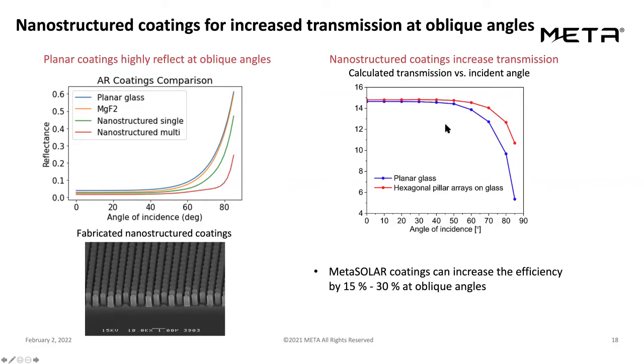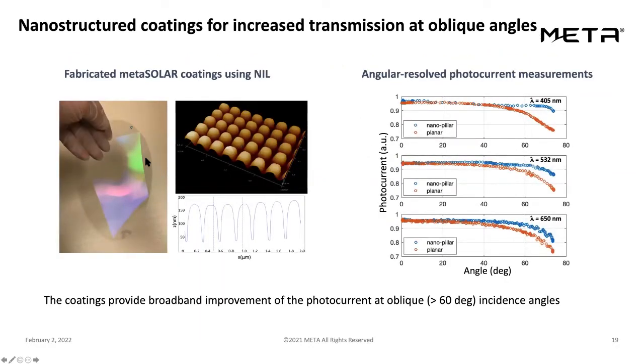And on the right-hand side, you see the total short circuit current for a 3-5 cell with an optimized coating in red, and then the planar glass is in blue. You can see an increase of 15% to 30% depending on the angle. We have fabricated these structures and applied them onto a solar module to see the efficiency increase. And indeed, we were able to replicate our theoretical predictions, and basically we have achieved a broadband improvement of the photocurrent at oblique angles. On the right-hand side, you can see the performance as a function of angle for various different wavelengths from 400 to 650 nanometers.